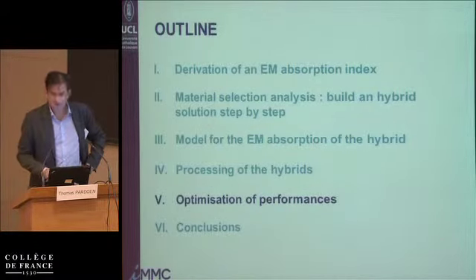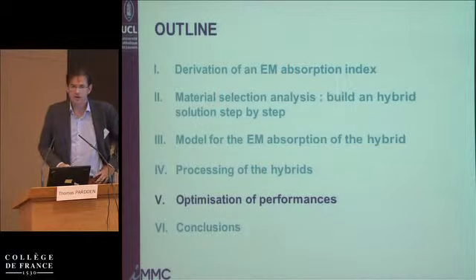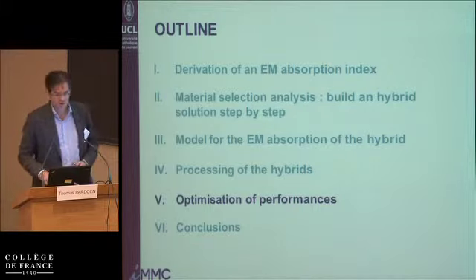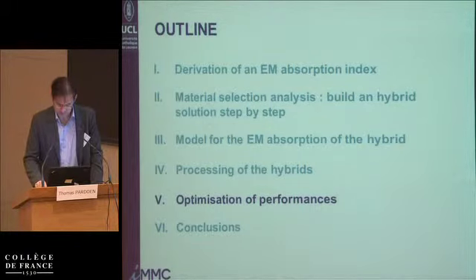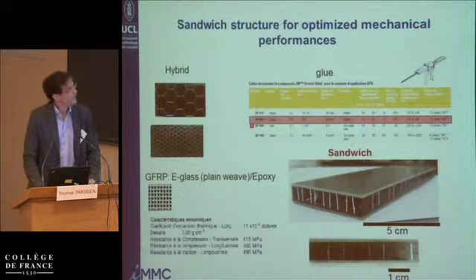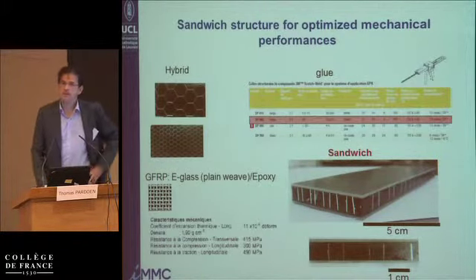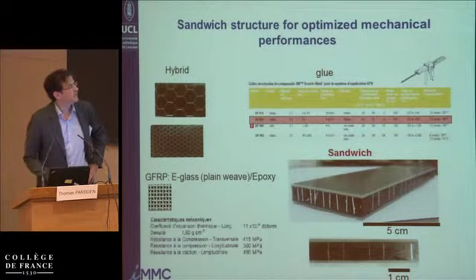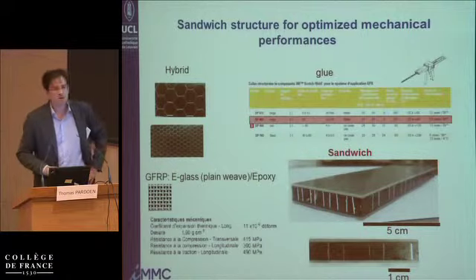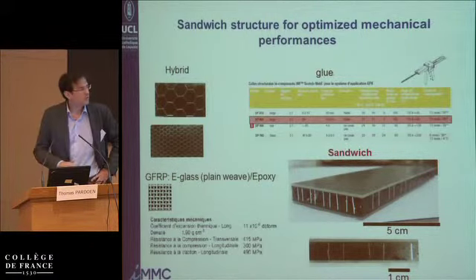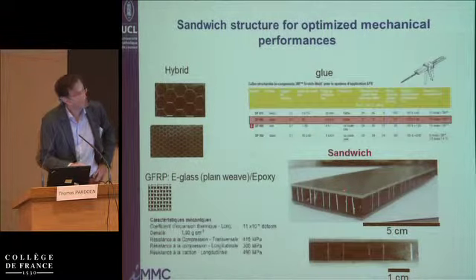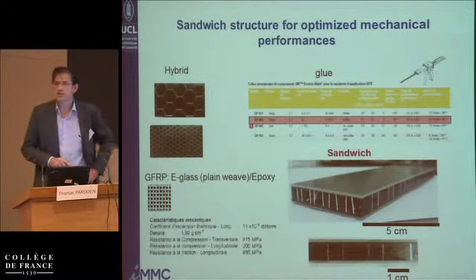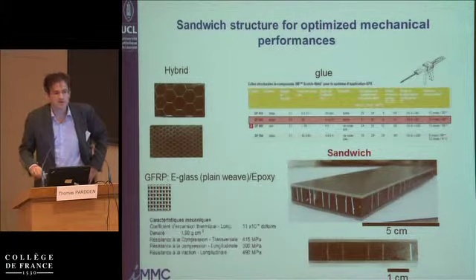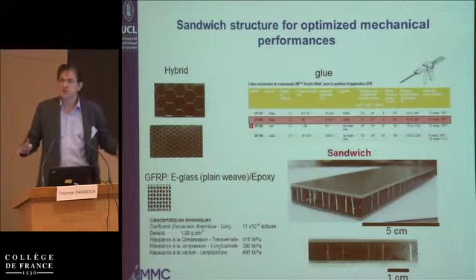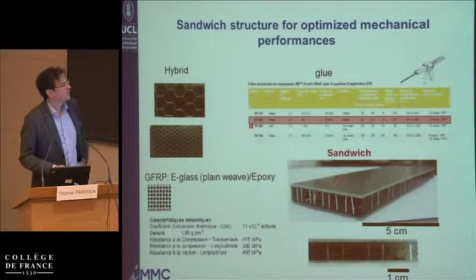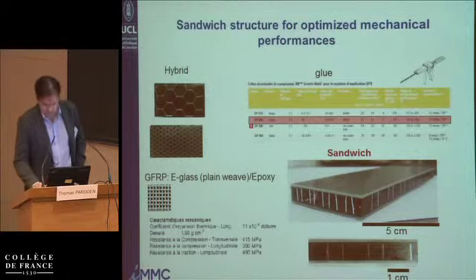And I will say now just a few words about the other properties. Electromagnetic absorption is okay, but we need to reach other performances to make this material useful in different applications. So to meet some mechanical requirements, for instance for aeronautic applications, we introduce this hybrid material as the core of a sandwich. This is the core material, and we use glass fiber reinforced polymers as face sheets, not carbon fibers or metals, otherwise we lose the entire absorption capacity of the material. We would reflect the incoming power again. So we use glass fiber material.